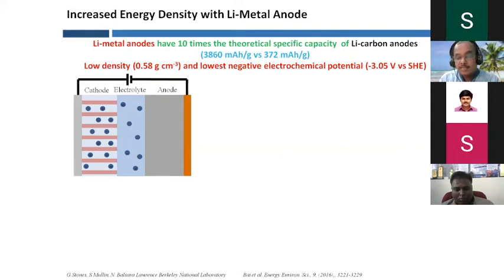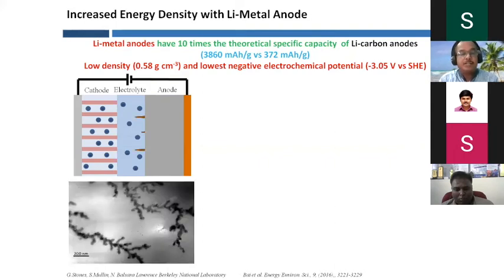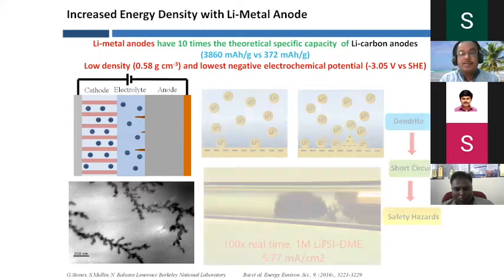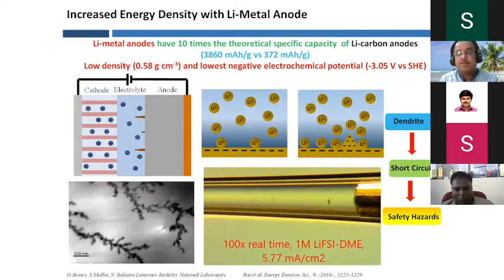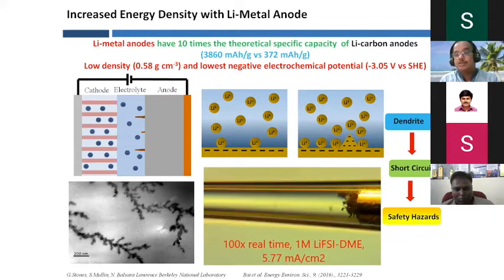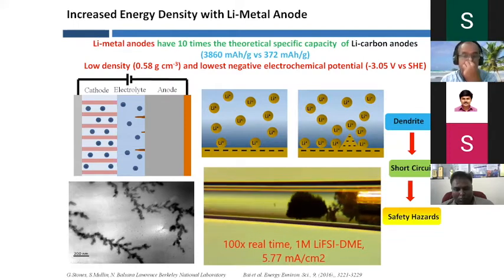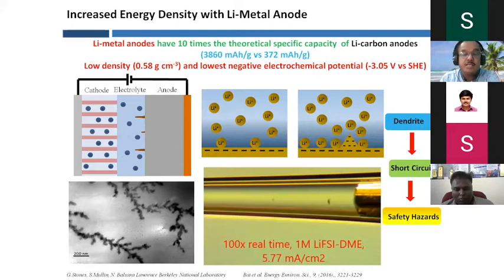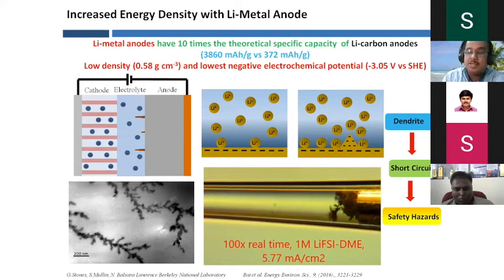With the existing lithium-ion battery technologies, everybody knows that lithium metal is highly reactive and can react with almost everything. Dendrite is the biggest problem. In real time, dendrites can immediately cause a short, then it starts to explode. So although lithium metal possesses a higher possible energy density, it may not be in a position to replace the existing technology, the lithium-ion electrolytes.